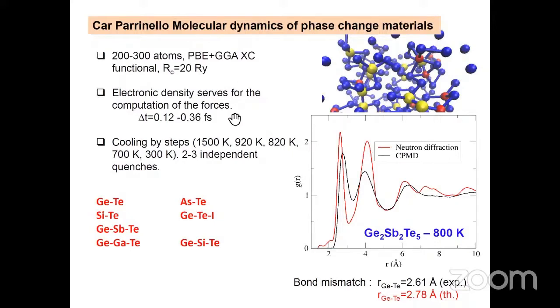So we cool the system by steps. Different systems have been investigated. I will focus today essentially on phase change materials. So here's the first figure that I would like to show, which is a Car-Parrinello simulation of GST in the liquid, at 800 Kelvin, compared to neutron diffraction results. And as you can notice, the agreement is very poor.